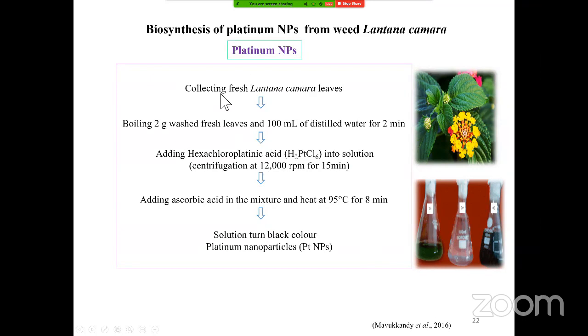2 gram of washed fresh leaves of this weed is taken and added to 100 ml of distilled water, and it is kept boiling for about 2 minutes. After that, hexachloroplatinic acid is added into the solution, and the solution is centrifuged at 12,000 rpm for 15 minutes. After that, ascorbic acid is added to the mixture and heated at 95 degrees centigrade for 8 minutes. The solution turns from green to black color, which indicates the formation of platinum nanoparticles.